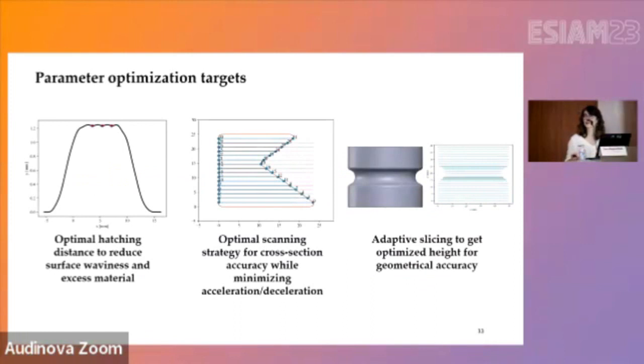This is what we have started already to implement in the model, trying to optimize the hatching distance in order to minimize the waviness of the top surface that we get and get better surface smoothness quality. We are optimizing the scanning strategy also for the cross sections to get higher geometrical accuracy and minimize also the number of variations in the nozzle direction in order to minimize the acceleration and deceleration of the nozzle that would affect the quality of the geometry. And also we are implementing another function for adaptive slicing to again improve the geometrical fidelity as we have different small features in the structure.